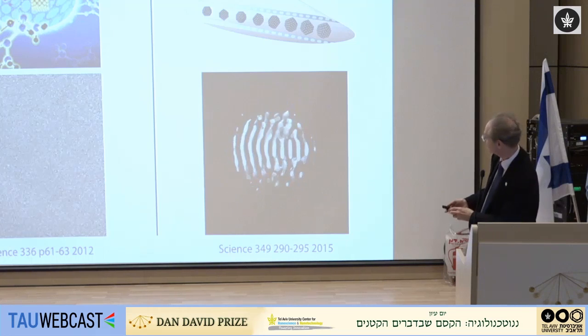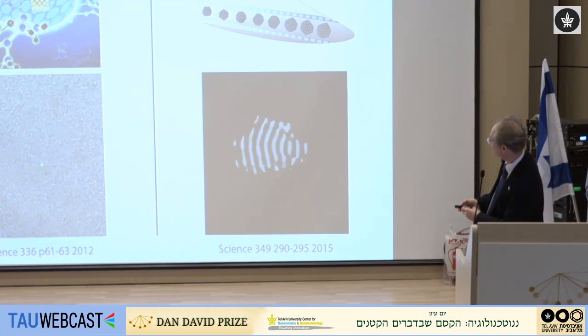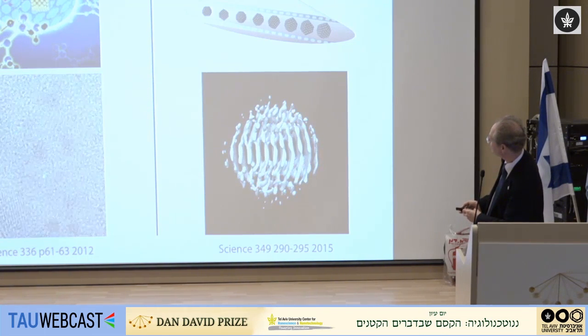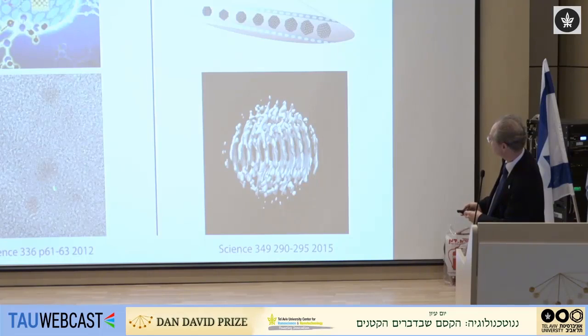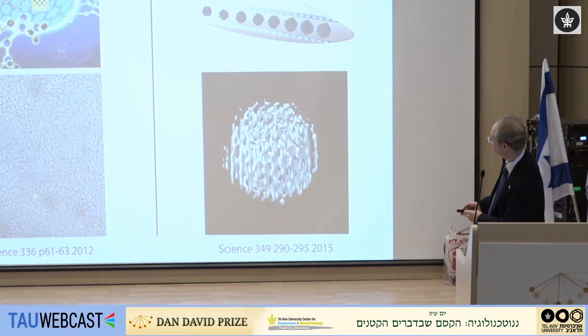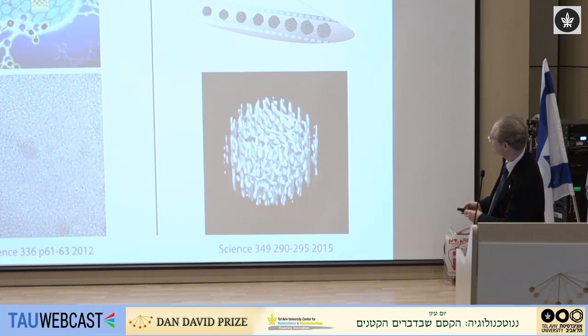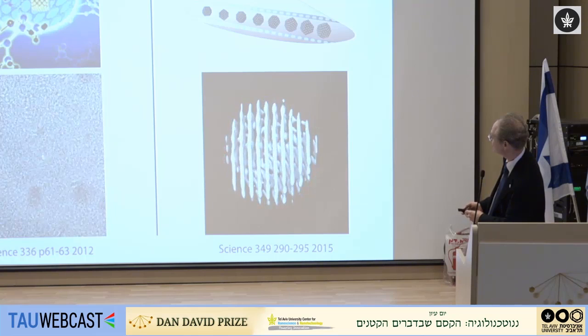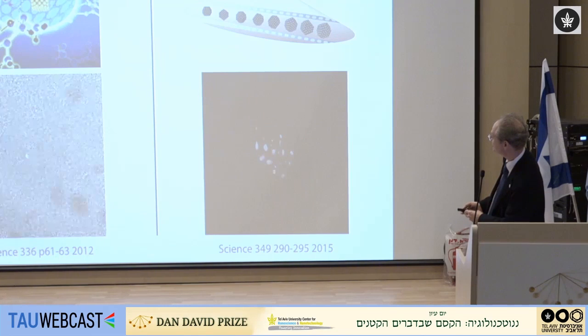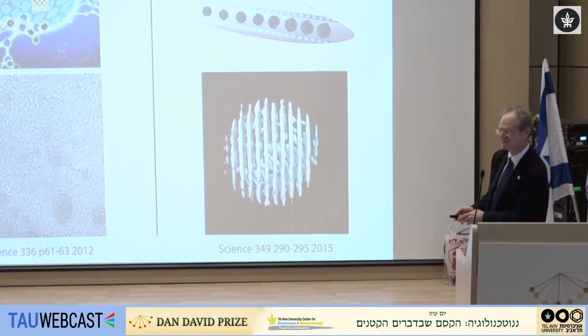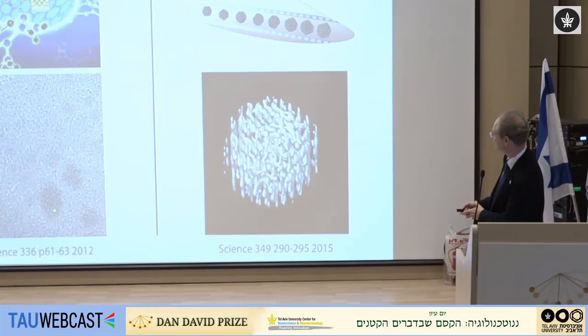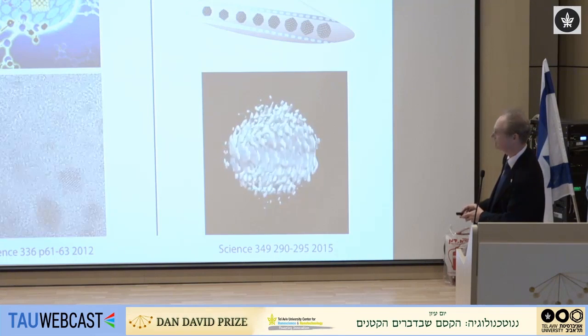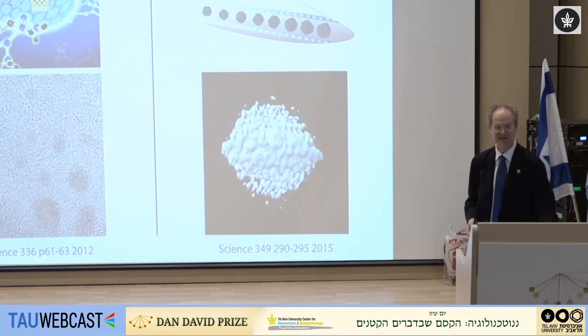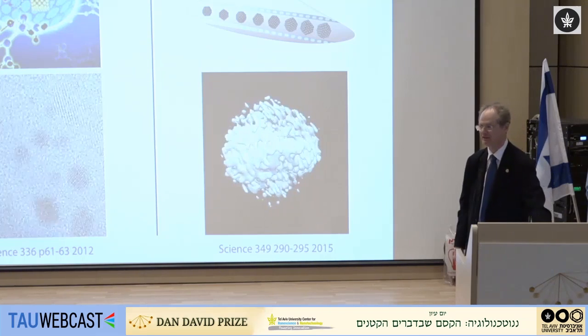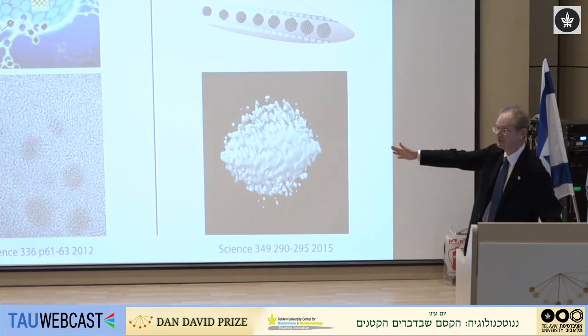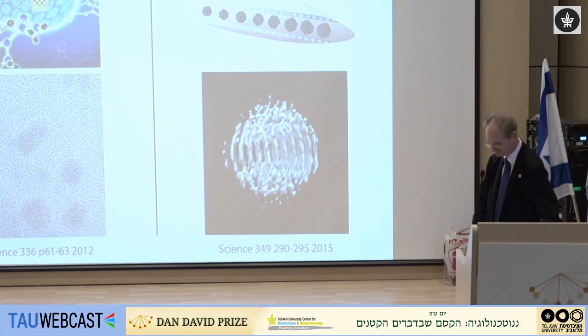There it is, starting at the beginning. So you can see here, you can't see too much, and then all of a sudden you'll start to see small crystals moving around, and they're moving a little bit faster at the beginning, and then they'll start to slow down. It turns out if you track those motions, their speed goes like 1 over the size, which is what you expect for a diffusive process. And you can see that periodically these crystals will fuse with each other, and those are the characteristics that happen inside that particular system. So here we can observe the growth of this crystal.